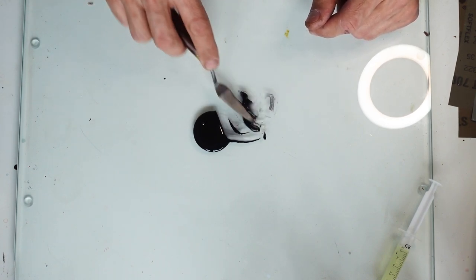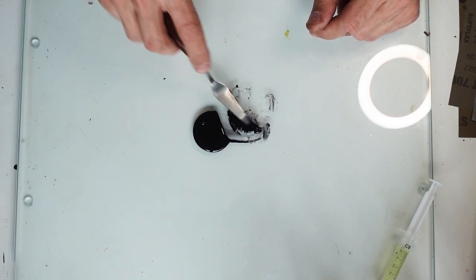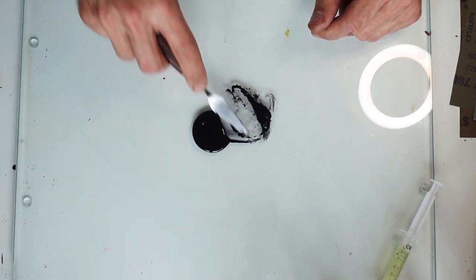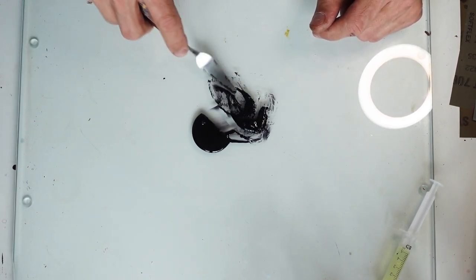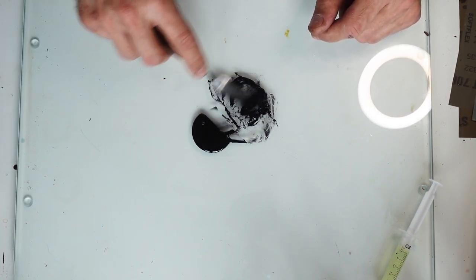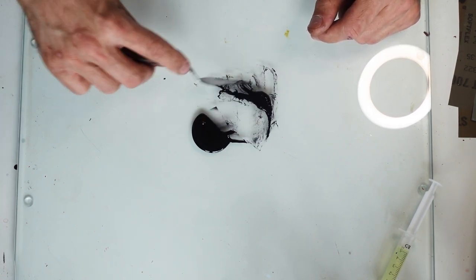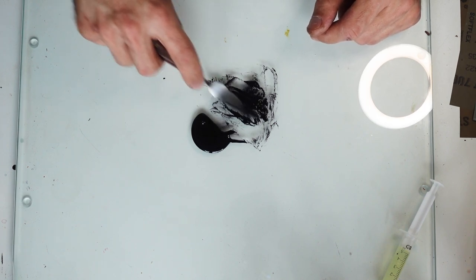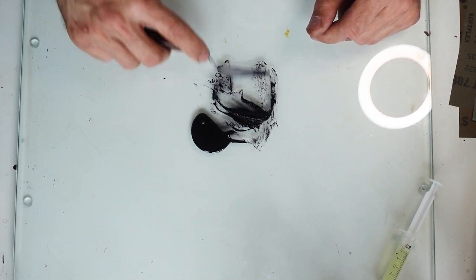So we have to add something, and this something is usually some water and protein, to simplify, and this water and protein is usually something edible. So it's sometimes gelatin, egg white, can be fresh egg white or dried egg white mixed with water, tofu, milk, soy milk, and some other stuff. And you can also add pigments on the different stages of mixing this mixture,